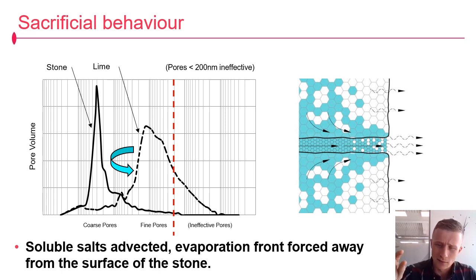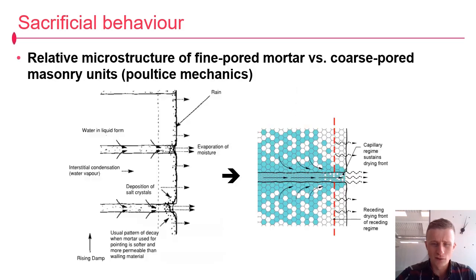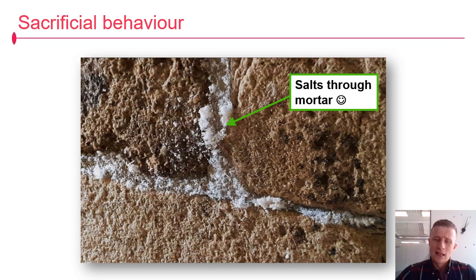So I've shown what's going on in the mortar joint around the arrises of the stone, in the spirit of how the SPAB published their findings. When you take a microstructural examination of both the materials and see the relative pore sizes, you can explain why there's a water management and implicitly a salt management process at work here. So poultice mechanics is at the heart of the sacrificial weathering phenomenon. We've seen this photo at the front. That's a bit of sandstone masonry walling with traditional lime mortar joints, and you've got soluble salt caked on the surface of the lime joint and nothing on the surface of the stone.